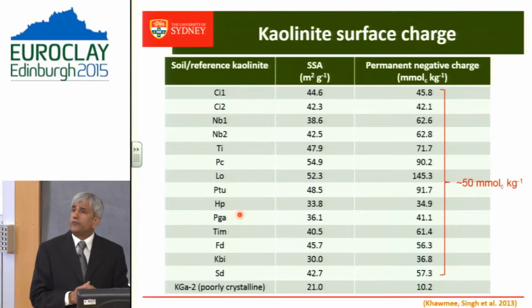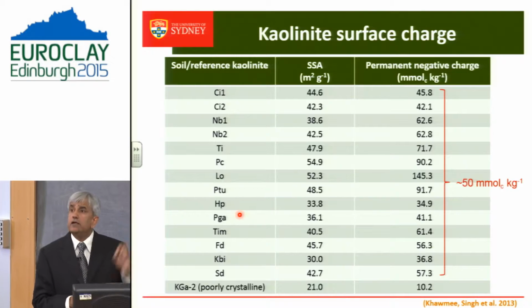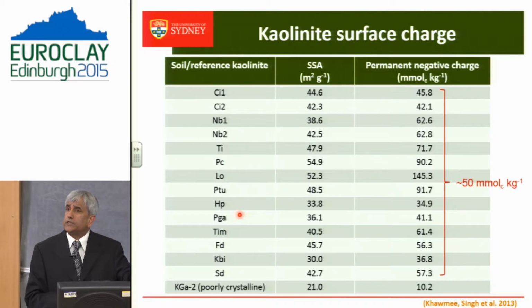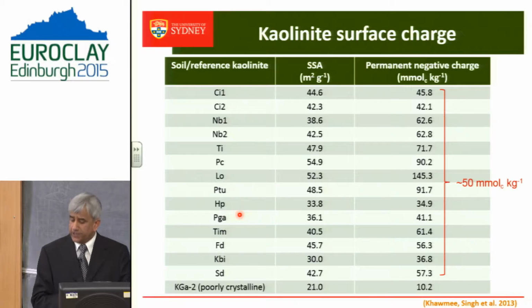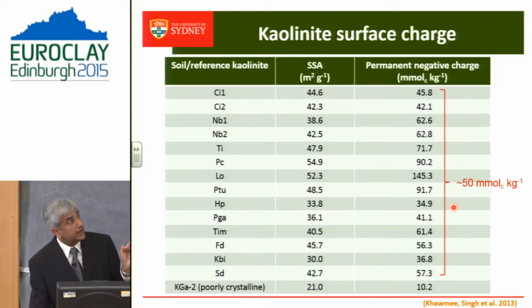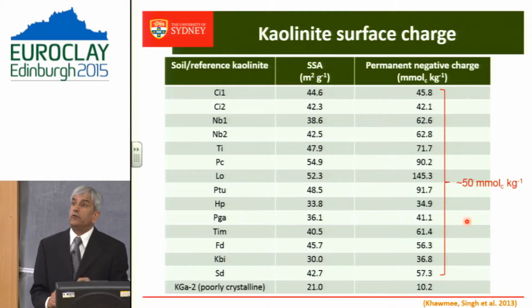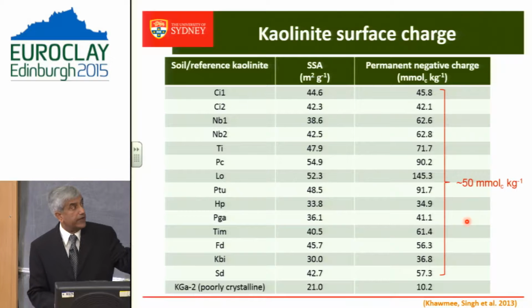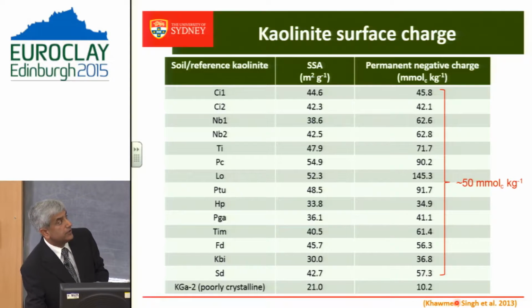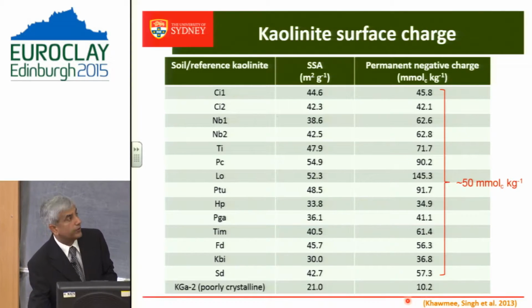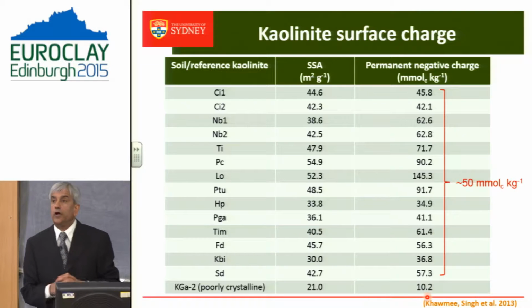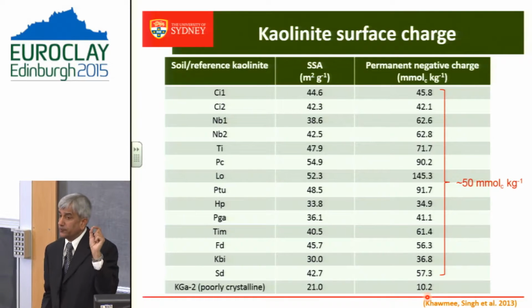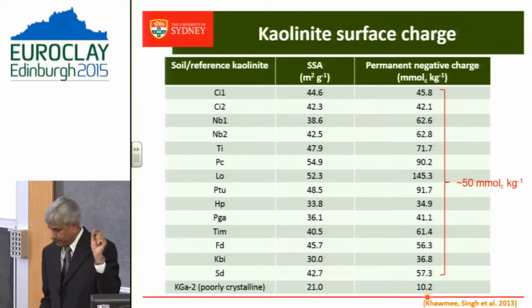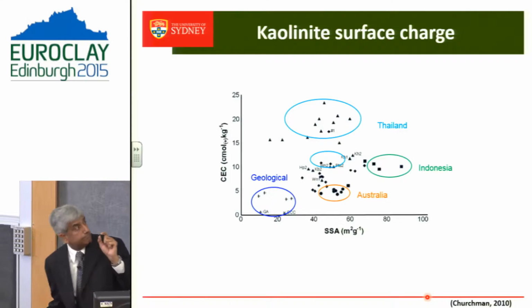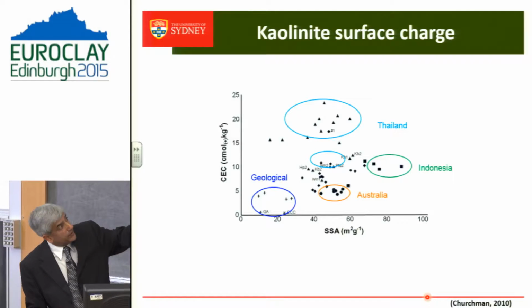What we have found in case of soil kaolinite is that all soil kaolinites we have looked at from at least half a dozen countries have at least 50 millimoles per kilogram cation exchange capacity, which is much bigger than what you would expect based on even the poorly crystalline phase or pure geological kaolinite. So there is some sort of structural defect, and this has been done here.